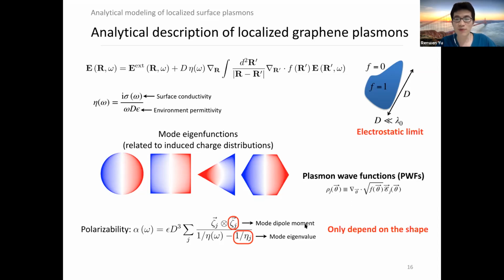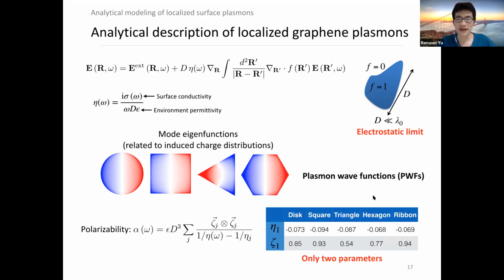This mode dipole moment can be calculated from the mode eigenfunctions, and the mode eigenvalue can be obtained straightforwardly after solving the eigenfunction. Note that these two parameters only depend on the shape of the nanostructure. It doesn't depend on its material, it doesn't depend on the size, it doesn't depend on the environment. It only depends on the shape. And after solving this eigenfunction, here are these two parameters for the first dipolar modes, obtained for these listed shapes, like discs, squares, or ribbons.